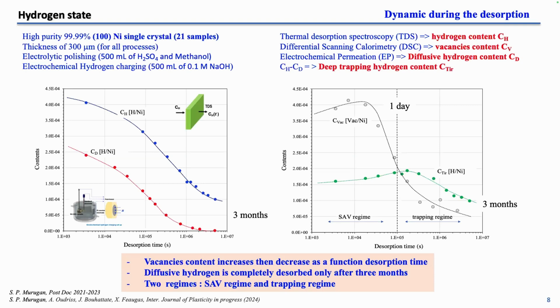We also follow the concentration of vacancies. We show that in the early stage we have a slight increase of the concentration of vacancies during the desorption step, and also an increase of the concentration of deep trapping in this same domain. In the second domain, we have a decrease of both components. It's interesting to compare both to question the two regimes. In the first regime, the concentration of vacancies is higher than the concentration of deep trapping, which means that we have more production of vacancies than the deep trapping process. In the second domain, the concentration of deep trapping is higher than the concentration of vacancies, which means that we have more trapping process than the superabundant vacancy process.